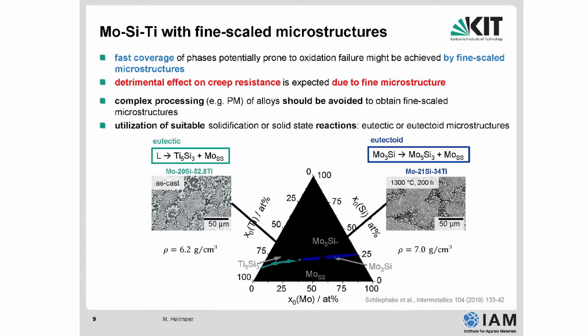Okay, I have to bother you with one phase diagram at least. Maybe you see a second one. So this is a melt projection of the ternary phase diagram between molybdenum, this is on this scale, silicon shown on this scale, and titanium shown on this scale. And when you look at the melt surface from the top, say from very high temperatures, you see different lines here, and these different lines reflect reaction pathways in the alloy. And we picked out two of the interesting ones.